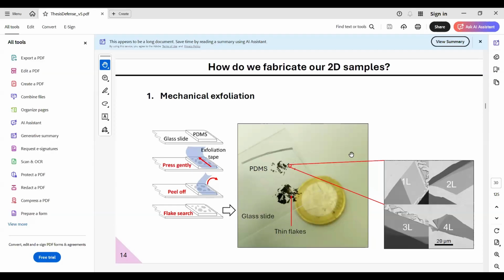Okay. Did you consider using oxygen plasma or UV ozone treatment to enhance this silanization process of the surface? We did try. We started using this and even exfoliating on top of our PDMS. You can get maybe flatter and higher material quality, less wrinkled, strained flakes, but it would produce much smaller films. As you see here, I can produce millimeter size thin flakes. So it's just patience and repeating it one time and another time. Of course, I think it could help if you would optimize this process very well, but we had so many things on our plates already, to see how long I need to put this in the oxygen plasma to get better flakes. I'm already doing it enough so that I produce very nice flakes anyway, and we just skipped this step. Okay.